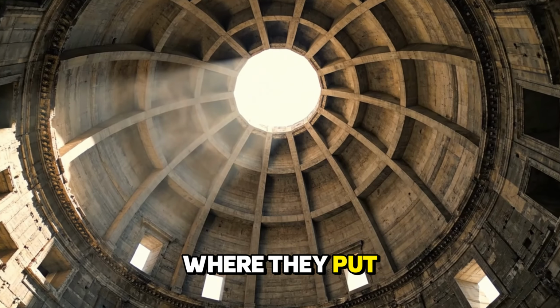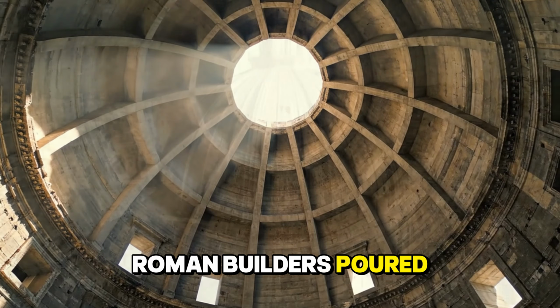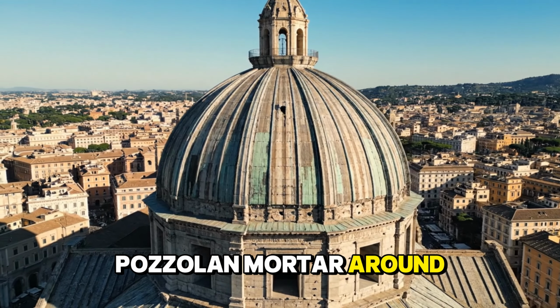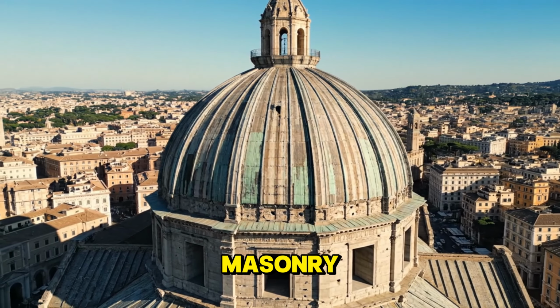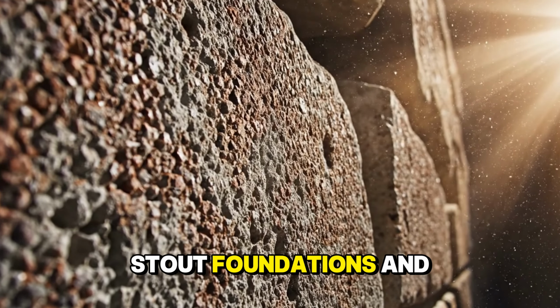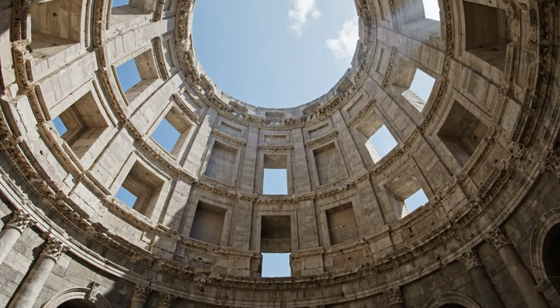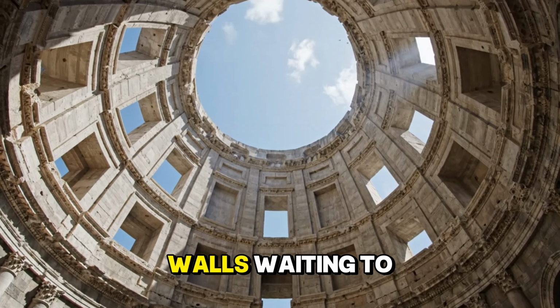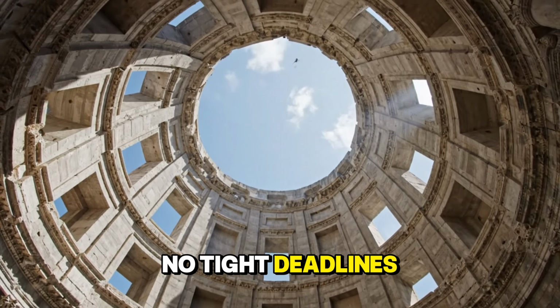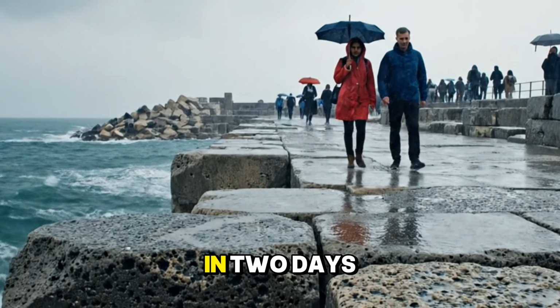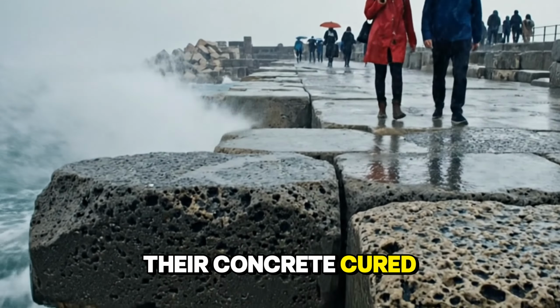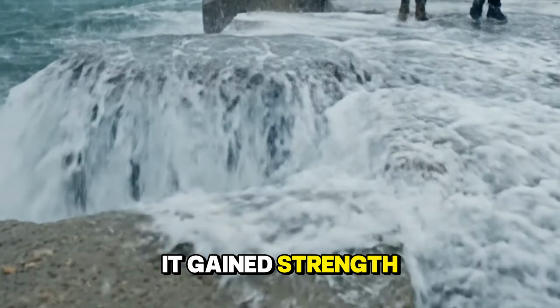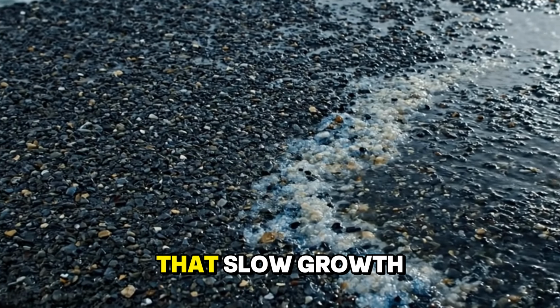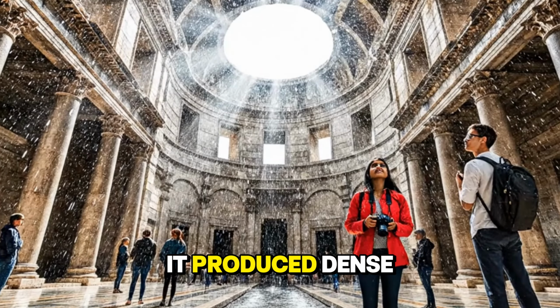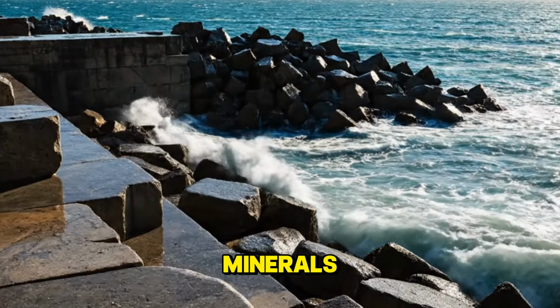Now look at where they put it. Roman builders poured that lime, pozzolan mortar around heavy aggregates and masonry. They did it in thick walls, stout foundations, and massive vaults. No steel cages sat inside those walls waiting to rust. No tight deadlines pushed them to strip forms in 2 days. Their concrete cured slowly. It gained strength over months and years. That slow growth mattered. It produced dense microstructures and stable minerals.